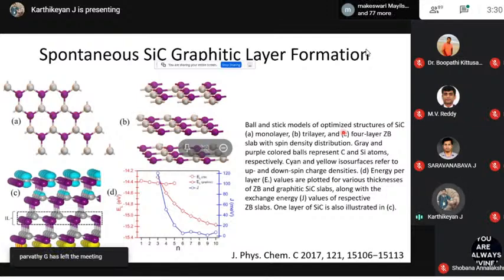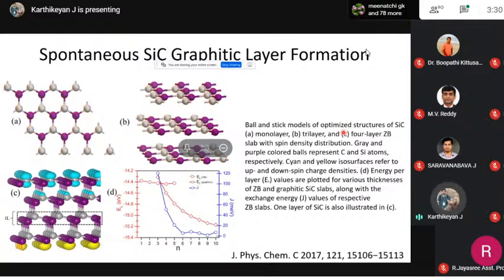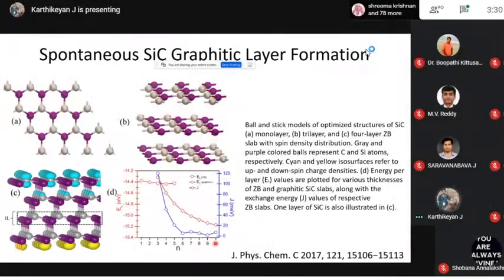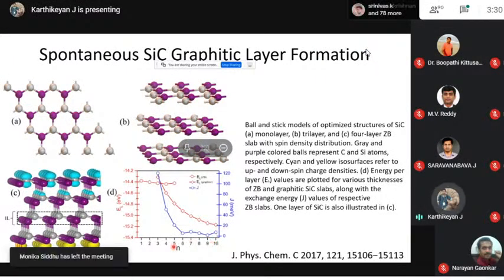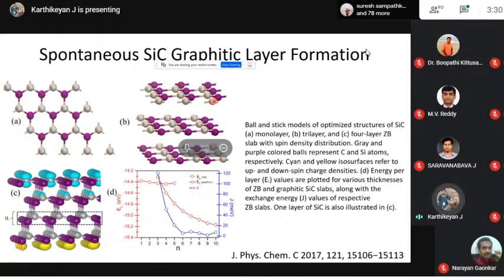We took the silicon carbide bulk structure, and we cleaved nano surface slabs, and first studied the surface slabs for different thickness. Here I have shown a surface slab of thickness 4. I have studied up to 10 atomic layers. When you reduce the thickness of the surface slab, suddenly after 3, it started forming graphitic layers. That was interesting, because when you start with the zinc blende kind of structure and reduce the size, it forms a graphitic structure.